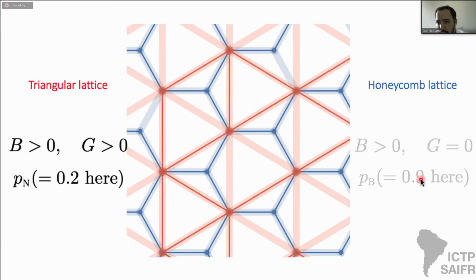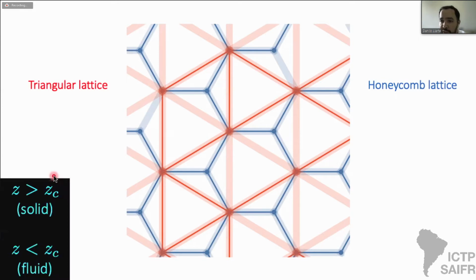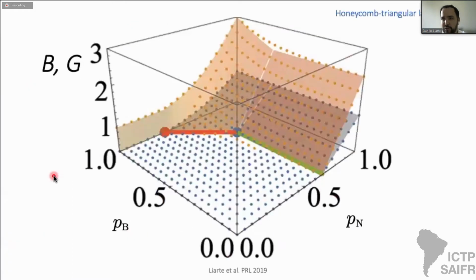Now in turn, the triangular lattice has finite bulk modulus and finite shear modulus, and I'm populating each bond with probability PN, which I take to be 0.2 here for this figure. Now the important thing is that I can control PB and PN so that Z minus ZC is greater than 0, in which case I have a rigid phase, or so that Z minus ZC is smaller than 0, in which case I have a kind of fluid phase. But there's more. I can control PB and PN to describe either jamming or rigid percolation. Remember that both of them describe transitions from an elastic solid to a floppy fluid, but that jamming has a jump in the bulk modulus.